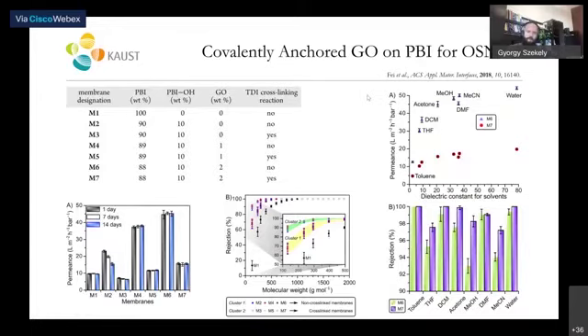Okay, so here you can see the final results for these membranes. We prepared a series of membranes and then we investigated what is the effect of cross-linking, what is the effect of the introduced hydroxyl groups, and what is the effect of the graphene oxide. So here you can see again that as you change the constituents of your membrane, you can change the permeance. And at the same time, the rejection can also change. And there is a trend.